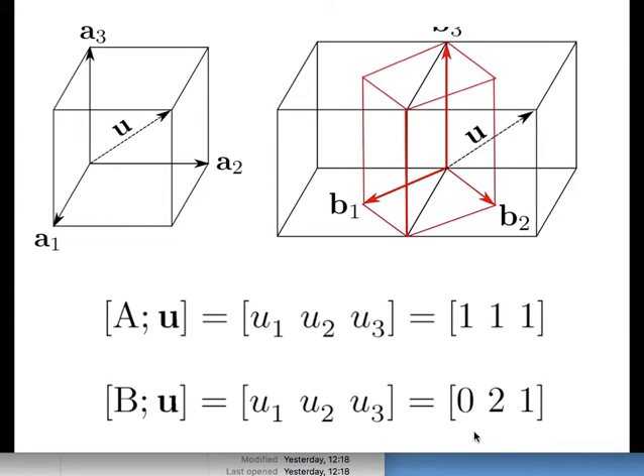But if I refer it to basis B, it has different components. It doesn't have any projection along B1. It's 2B2 and 1B3. So the components of the vector are different in different coordinate systems, and you could say that the 0, 2, 1 direction in crystal B is parallel to the 1, 1, 1 direction in crystal A. That's how we express orientation relationships: that a particular direction is parallel and a particular plane is parallel between the two crystals, okay? Everyone happy with that?